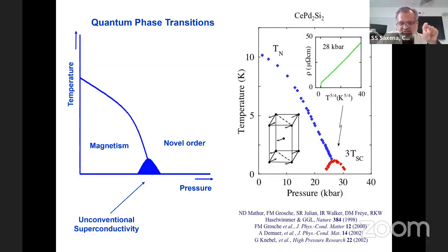When it retracts, if there's something low energy enough, it'll trap it, and that creates a condensate or Cooper pair type of thing, which in this case is created by magnetism. So the final point here is that you have superconductivity created by magnetic fluctuations, i.e. magnetism, not destroyed by magnetism in a simple way as in normal superconductivity. And you have a state which is now not anymore the canonical Fermi liquid state.